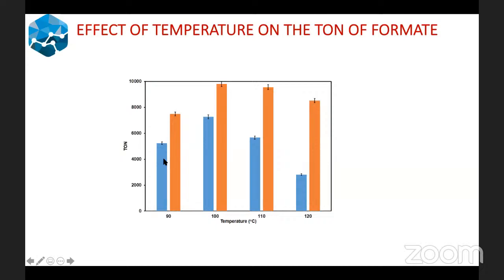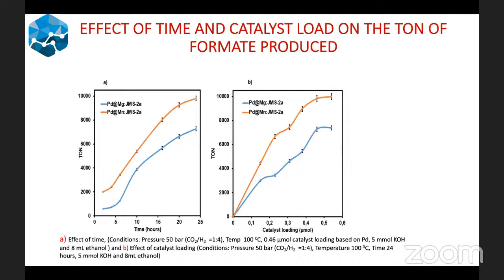And for the magnesium-based MOF, the blue bars, the turnover number increases from about 5,000 to above 7,000 at 100 degrees Celsius. And beyond 100 degrees, there is a significant decrease in the amount of formate that is produced. We also looked at the effect of time and catalyst load on the turnover number of formate produced. And again, an increase in time results in an increase in the amount of formate that is isolated. As you can see, the turnover numbers here are increasing. The same also applies when you increase your catalyst load, the turnover number also increases.